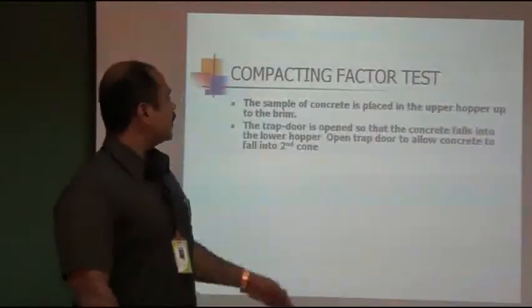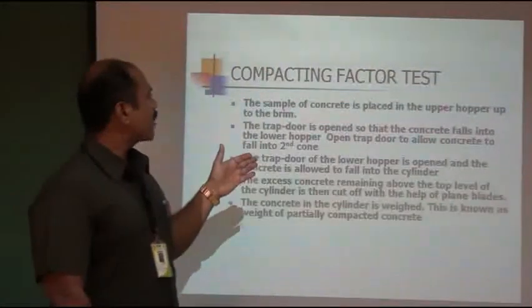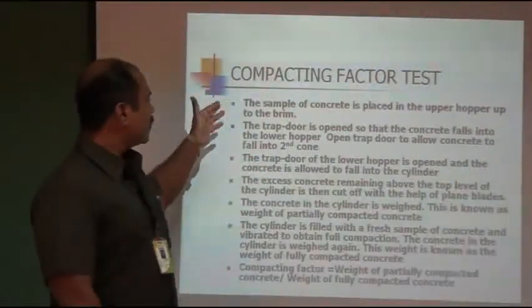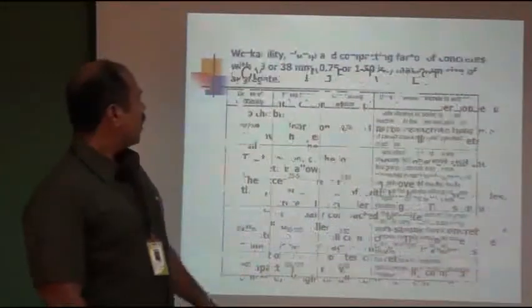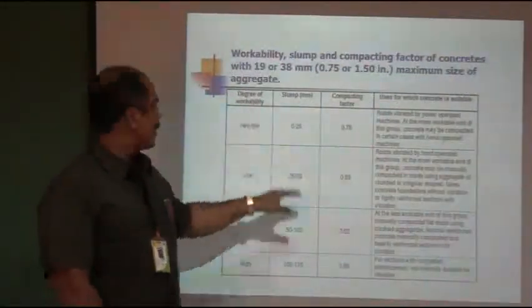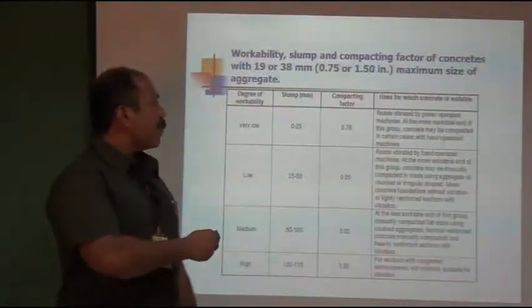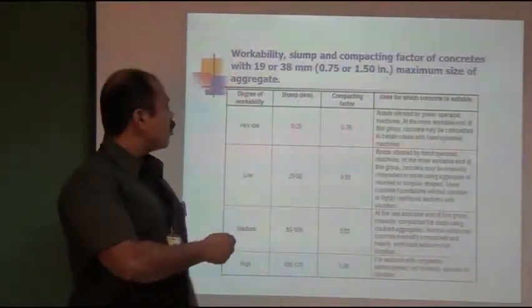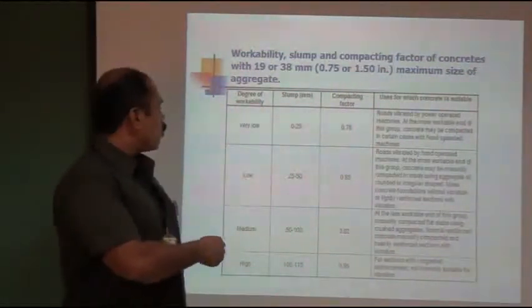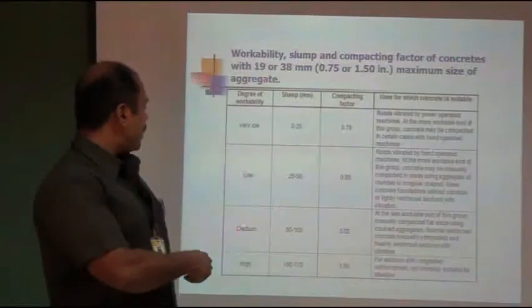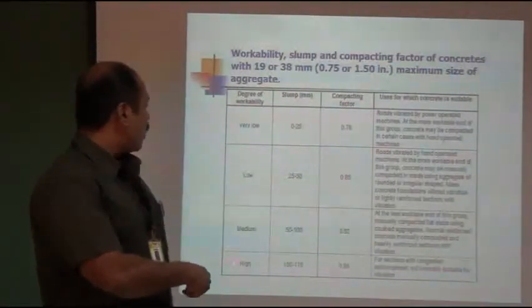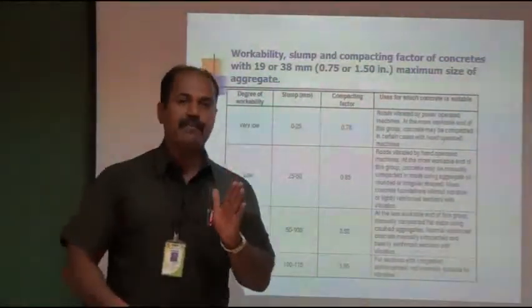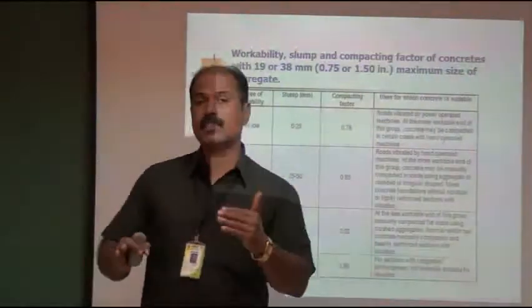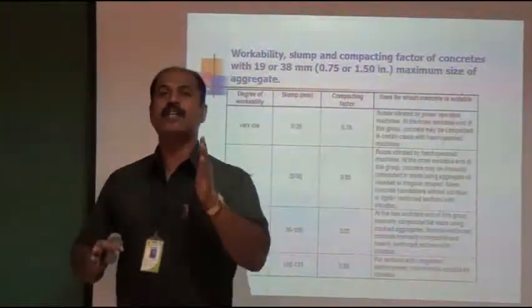So this is the testing procedure of the compaction factor of the concrete: how to test from the first hopper to the second hopper, as per the Indian Standard. What is the value required for the compaction factor? Very low means 0.78, low compaction factor is 0.85, medium is 0.92, and high compaction factor is 0.95.